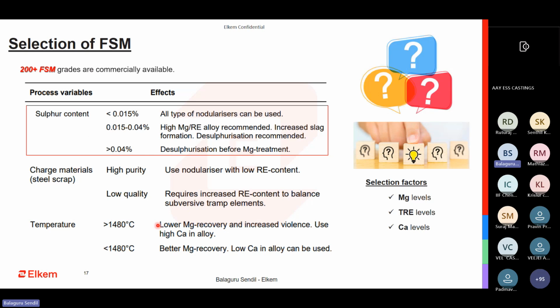Again, when you do this, the majority of the magnesium is going to be desulfurizing. Magnesium is going to tie up with sulfur, form bigger slag and float out. So if you're using 9%, your residual magnesium that you're measuring of 0.035, the majority of it would be the free magnesium wasted. Whereas when you have less than 0.015 sulfur, the correct amount of sulfur in your base metal, and you are using a 5% magnesium FSM and still getting 0.035, then the majority of the magnesium you are measuring is going to be very useful, and for that, very minimum inoculation will give you excellent microstructure with high nodularity and nodule count.